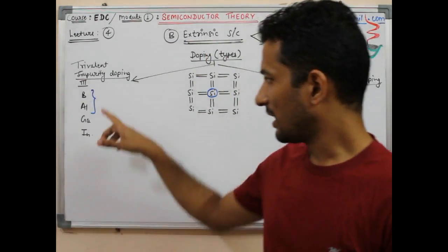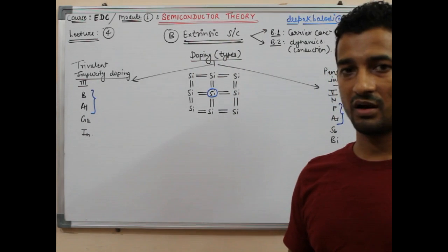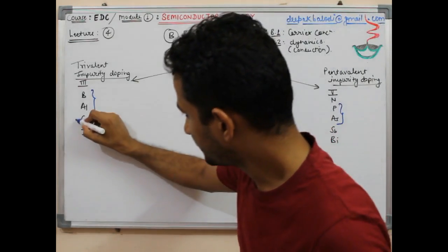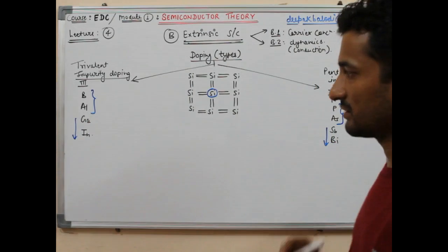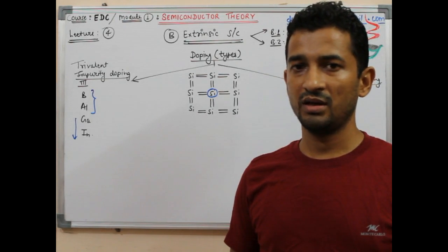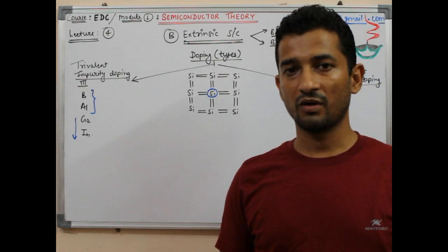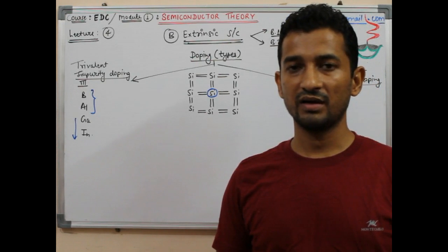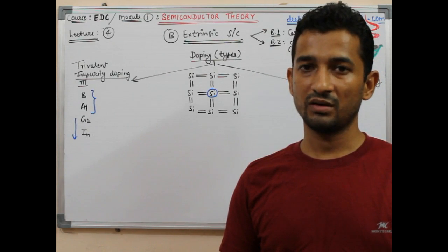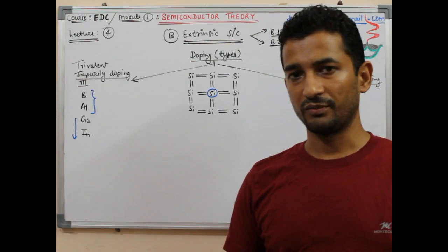There are several reasons for that. Boron and aluminium find a better electronic affinity, and similarly phosphorus and arsenic find a better electronic affinity with the silicon. As well as, if we go to the lower side like this, or like this, then the atoms become heavier and massive, larger in size. So these impurities lower in the columns are not in good support of the integrated circuit technology. Being heavier and larger in size, they can harm the silicon wafer, and their diffusion and ion implantation processes, which are the processes to dope something inside silicon, are not very well supported by the silicon.